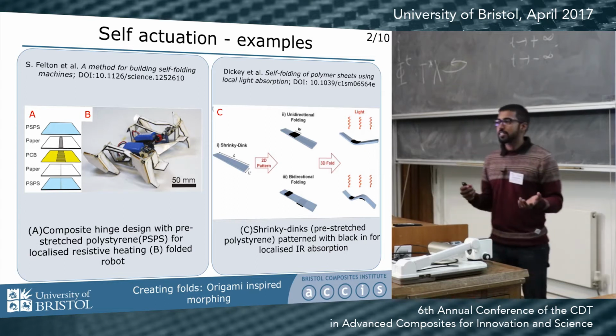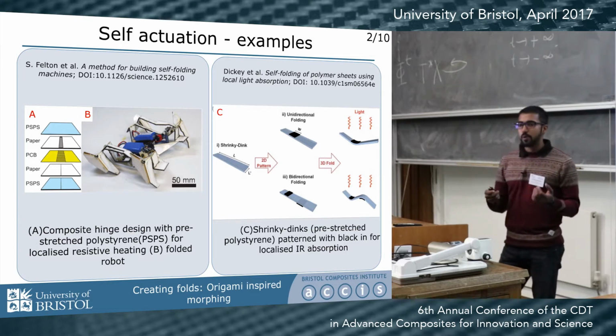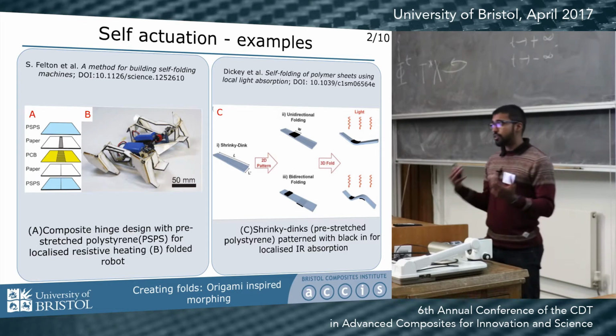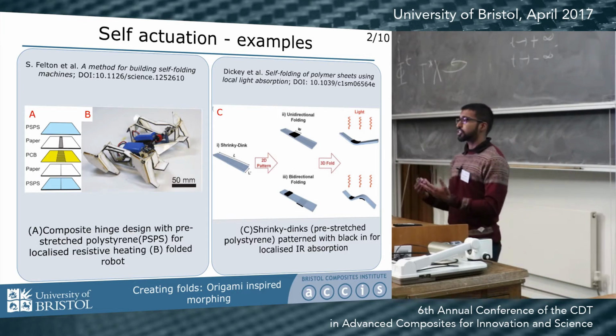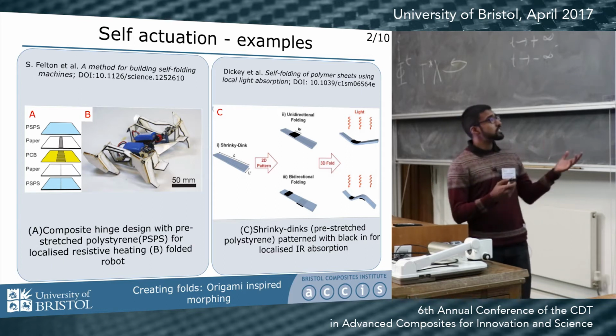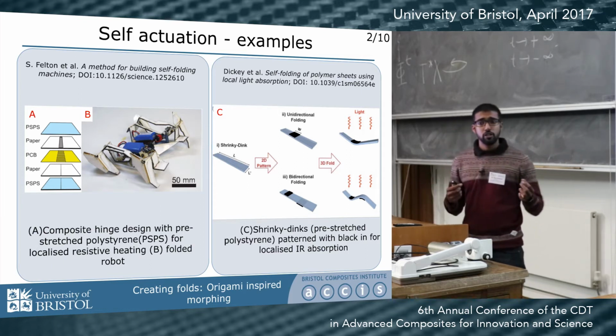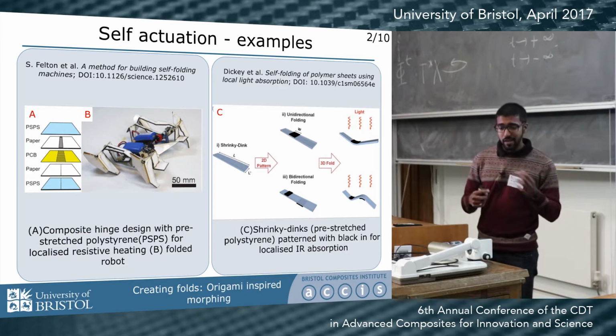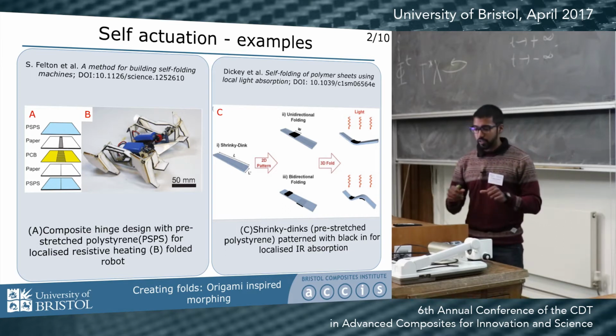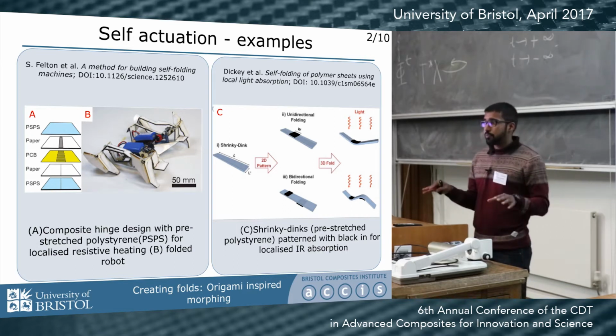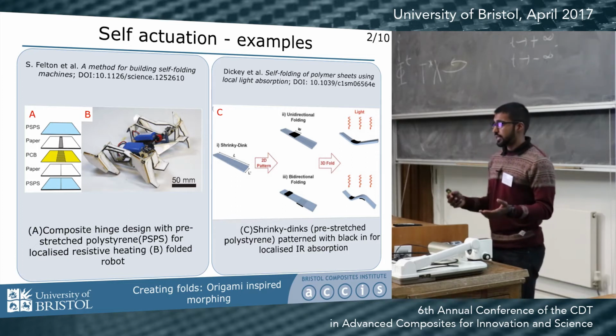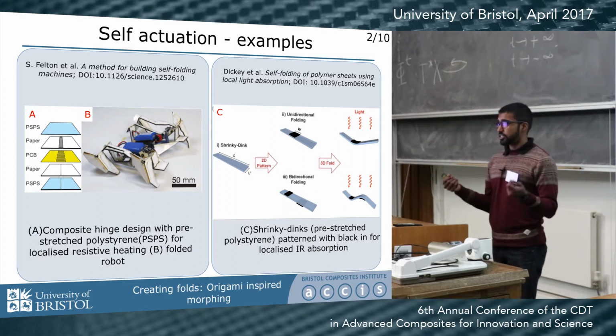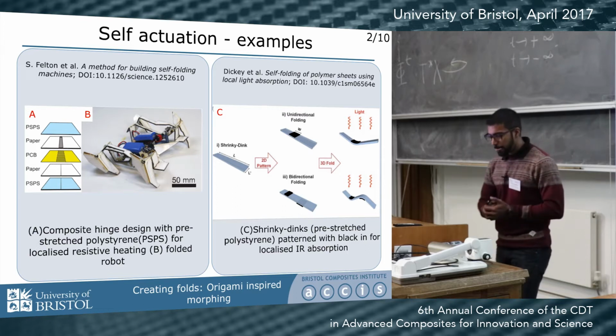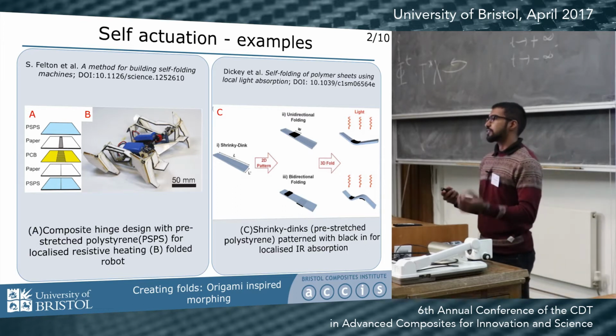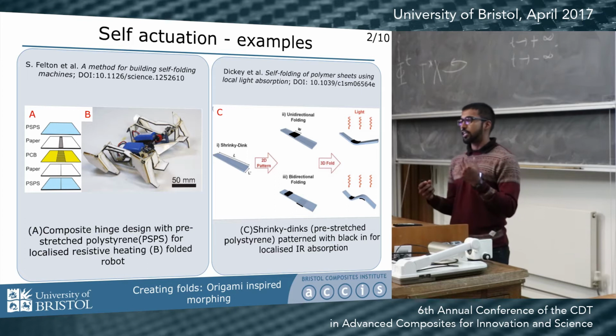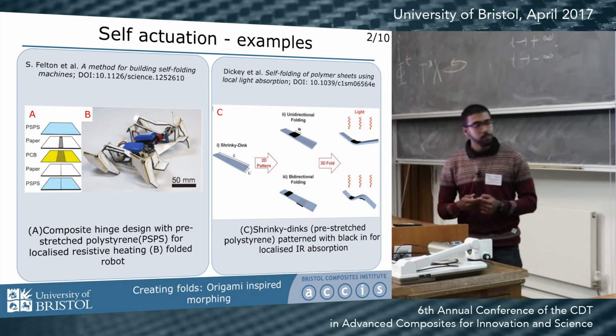In synthetic smart systems, morphing is mainly realized by means of a strain mismatch. And there are different ways to realize this differential in a substrate. As we shall see from the examples, a common approach is to use shape memory alloys or polymers in a composite fashion to define hinge regions. These shape memory materials require a programming step where they are stretched at elevated temperatures followed by cooling with the strain on. Heating of the material above its glass transition temperature releases the internal locked-in strain, driving the transformation.